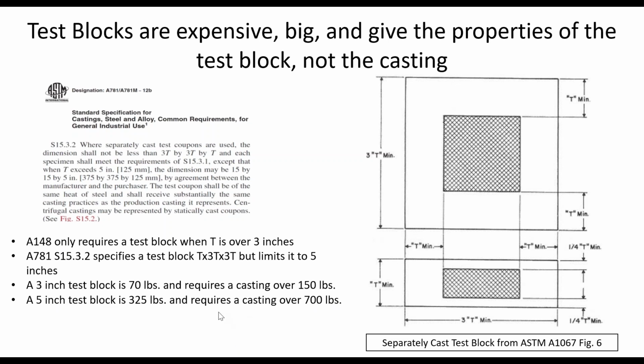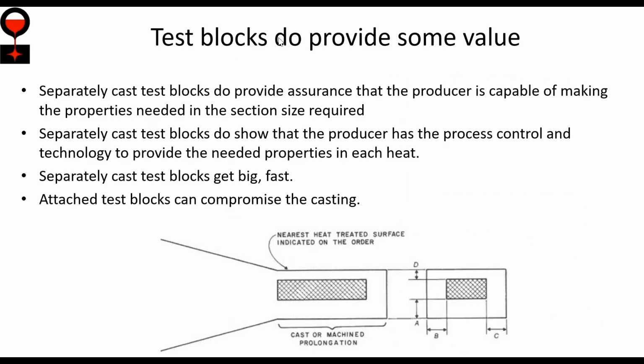But special test blocks can be really useful. So the test blocks separately do provide a real value. And the value they provide is if you make me qualify to make a separately cast test block, it means that I have the technical skills, the process disciplines, and the process capabilities to meet the properties you need in the section size of your casting. So if you ask me to make a test block, what you've proven is that I have the skill and the technology to meet the properties in a test block, and you assume, and correctly so, that that means I should have the technology to make a casting with those kinds of properties.